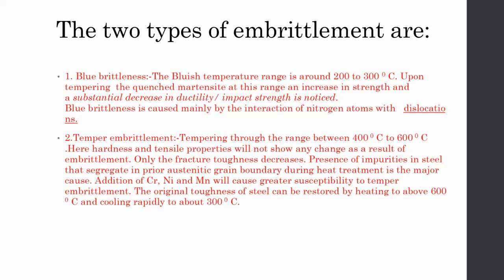The original toughness of steel can be restored by heating to above 600 degrees centigrade and cooling rapidly to about 300 degrees centigrade. So temper embrittlement is a reversible process. It always comes back to its original condition by further heat treatment. But in the case of blue brittleness, it is an irreversible process. Because once this particular blue brittleness takes place, the material cannot be used, it will be brittle only.